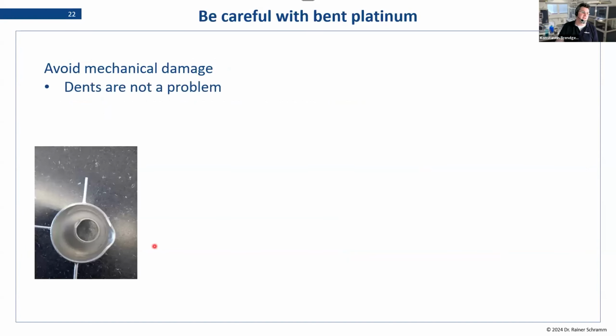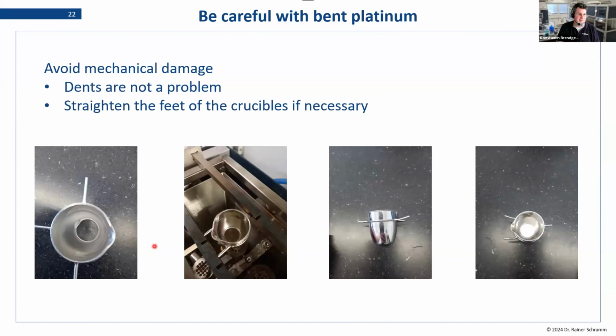General handling advice, just to sum it up. The samples or the platinum get dropped. It just happens in laboratories. So having a dent in your crucible is generally not a problem, although you want to be careful. Remember the little tray I showed in one of the earlier sessions? It's a good idea for handling because it avoids you and your staff dropping stuff. So dents usually don't matter really. It increases the cleaning time in the ultrasonics, but otherwise it doesn't really matter.